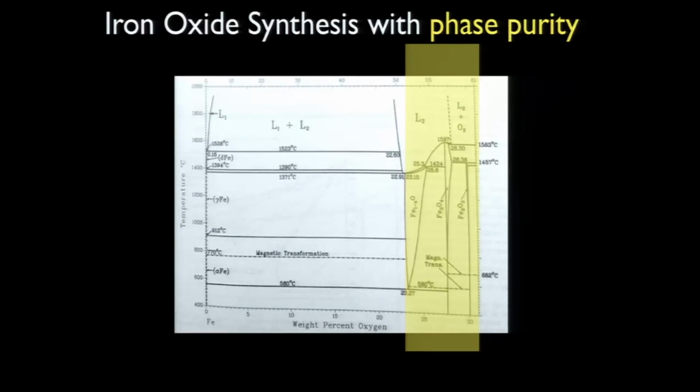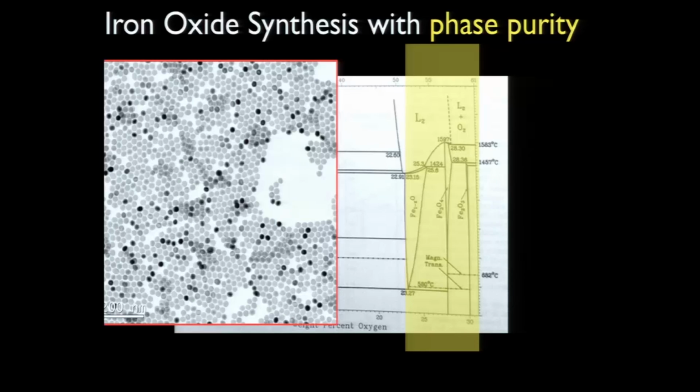So basically the bottom line of all of this, the take-home message, is that we think somewhere between 25 and 28 nanometers is an optimal size to make the best MPI particles that will give you a very strong Néel relaxation even in applied field amplitudes of 20 millitesla.